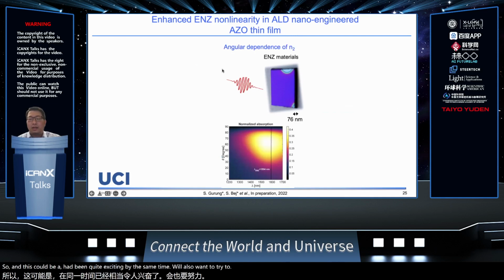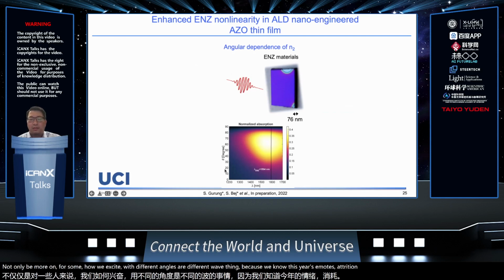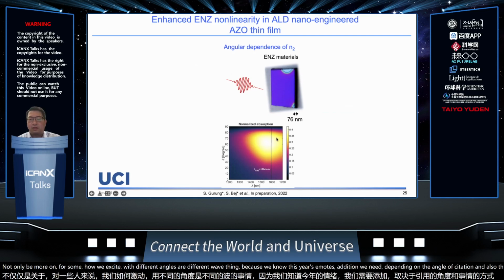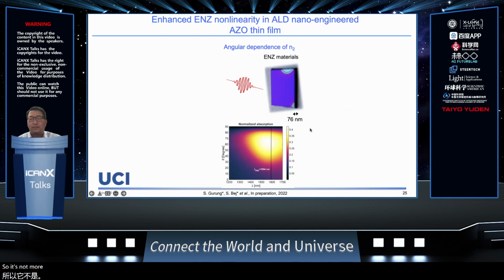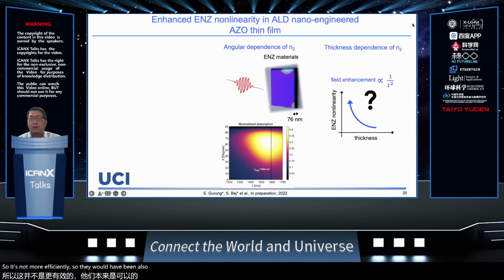So this has been quite exciting, but at the same time, we also want to look a little bit more at, for example, how we excite with different angles or different wavelengths, because we know this ENZ mode excitation really depends on the angle of excitation and also the wavelength. So at certain wavelengths and angles, you can excite this mode more efficiently. We have also been looking at the thickness dependency, because we know that this kind of optical confinement is inversely proportional to the thickness squared. So we want to see if we can reduce the thickness in order to enhance the nonlinearity here.